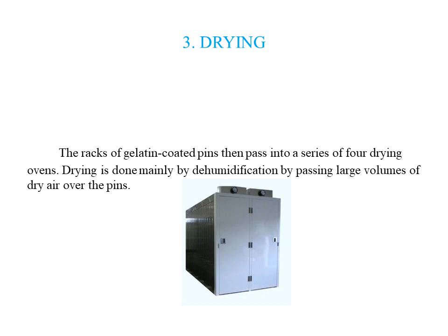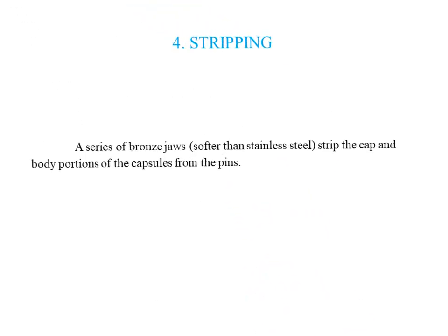Over-drying must be avoided as this could cause the film to split on the pins due to shrinkage, or at least make them too brittle for the later trimming operation. Under-drying will leave the film too pliable or sticky for subsequent operations.